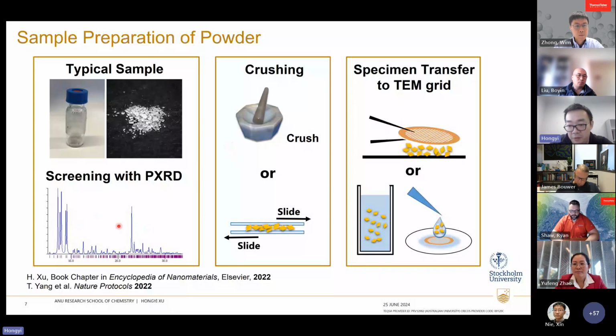So if something is sensitive to the vacuum in the TEM, what we measure at the end should match what was in ambient air. For example, we can use it to compare if a sample has been modified by a procedure we do during the MicroED process. And as I said before, crushing and depositing the sample can bias the small crystallites that end up on the grid. I wouldn't go into too much detail, but for any quantitative analysis, the sample preparation part has to be more bias-free.